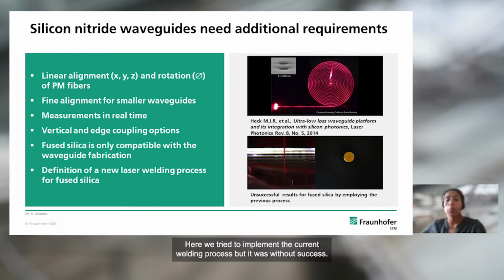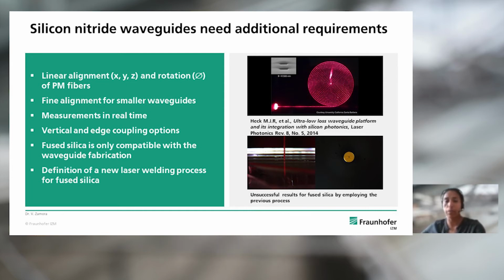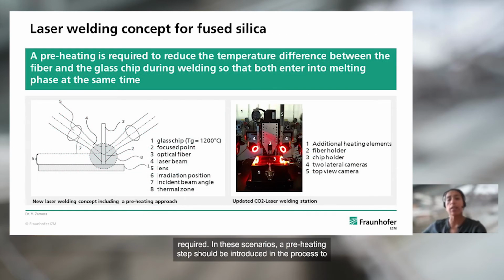Here we tried to implement the current welding process, but this was without success. The background lies in the high Tg value of the fused silica, which is about 1200 degrees Celsius. Therefore, the definition of a new laser welding process for fused silica is required. In these scenarios, a preheating step should be introduced in the process to reduce the temperature difference between the fiber and the fused silica chip during welding, so that both enter into the melting phase at the same time.